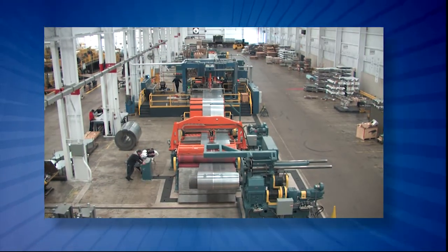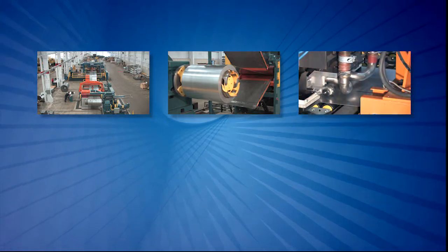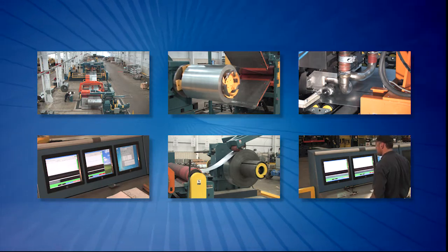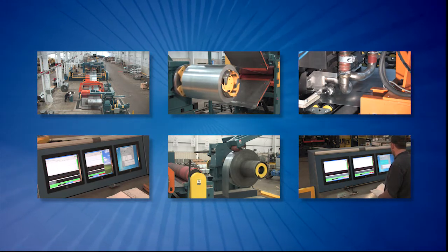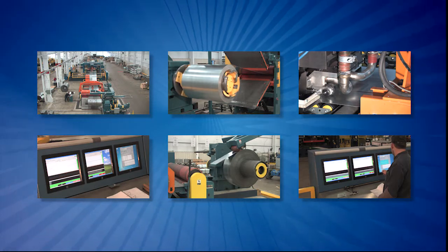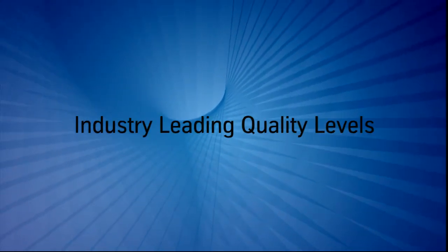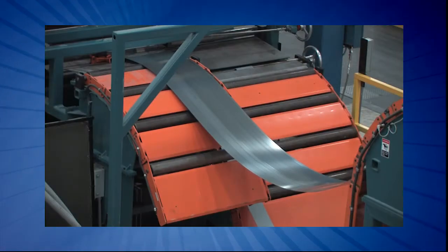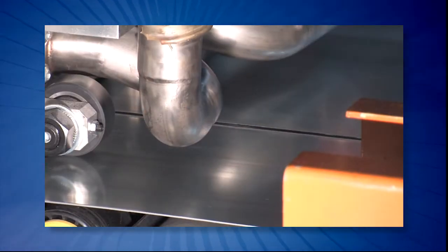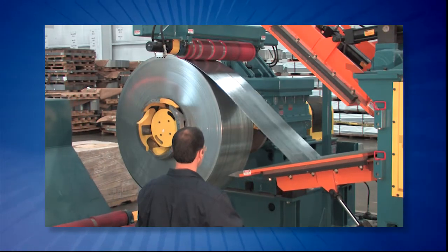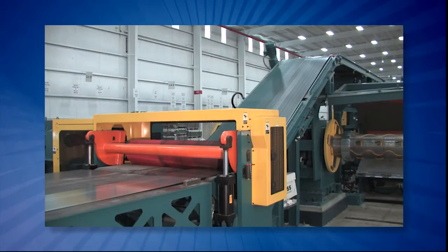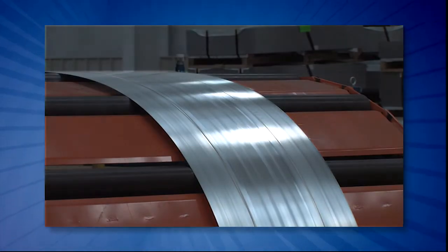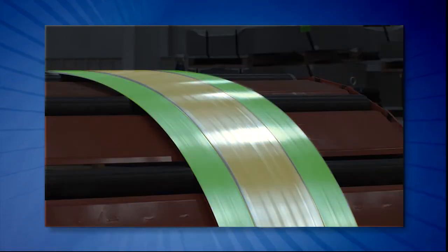The Tailor Welded Coil process includes uncoiling, welding, monitoring, and recoiling that utilize the same continuous feed weld process, quality monitoring system, and criteria that provide our welded blank customers with industry-leading quality levels. The component coils are uncoiled and threaded through the line. Two coils are then joined simultaneously with a laser welding seam. Additional coils can be added to the Tailor Welded Coil assembly by passing the welded coil through the welding line a second time. The most cost-effective weight savings typically are made from two welding seams and three coils.